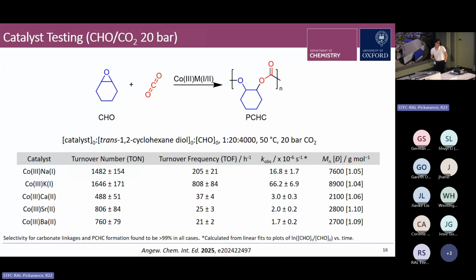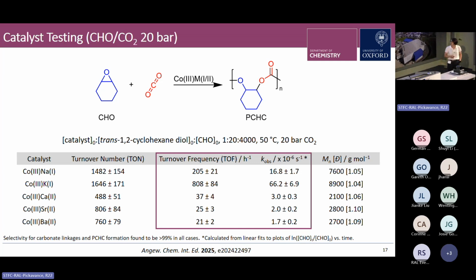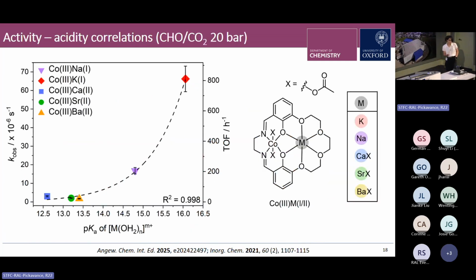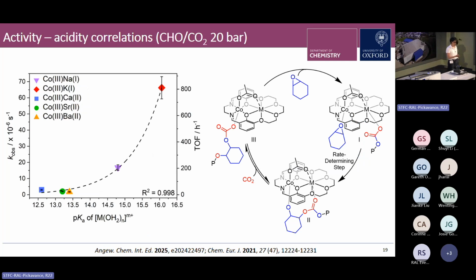So the same series of catalysts were also tested for the copolymerization of CHO and CO2 at 20 bar CO2 pressure and 50 degrees. And again, all 5 catalysts were successful in making a polycarbonate with narrow dispersity. But again, we see significant differences in catalytic activity across the series, with the cobalt-potassium combination being the highest performing. So if, as before, we plot these activity values versus the S-block metal Lewis acidity, we see a similar type exponential correlation. And similar to before, we can rationalize this exponential correlation with respect to the proposed catalytic mechanism, which